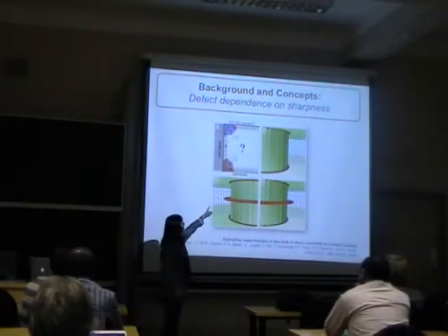And next, this is from the Abbott group as well, and the Cameron group. Here, this is a simulation of an experiment that they were doing with micropillars. They had micropillars that are around 10 microns in diameter, and there's a glass substrate at the bottom and at the top, and it was treated so that there's perpendicular homeotropic anchoring. And surrounding it was nematic liquid crystal. The nematic liquid crystal will want to be perpendicular to all the sides. So the question is, how does the nematic liquid crystal want to deal with the corners, right? With the sharpness, it has to deal with this with either a bend or splay configuration that results in a plus or minus 1/4 winding number.